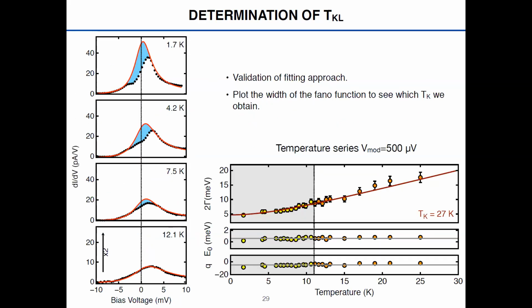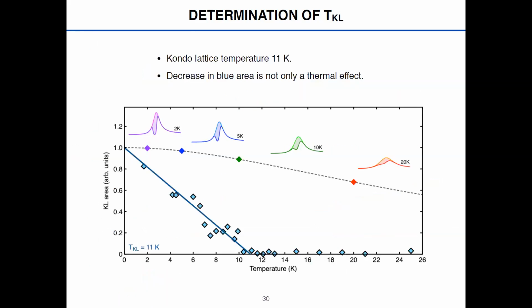To try and validate this fitting approach, we basically do the same thing we did previously with the Kondo resonance. We're going to draw a plot showing the full width at half maximum as a function of temperature. And what we obtained in this case is, again, the same Kondo temperature, 27 Kelvin. So in a way, we are validating our fitting approach. If now we plot how this blue area evolves with temperature, we get this plot here. This is how the blue area is decreasing with temperature, and more or less it becomes negligible close to 11 Kelvin. So this is the Kondo Lattice temperature we propose. And this behavior cannot be only due to an increase of the thermal energy.